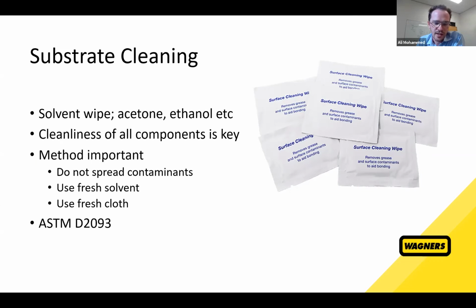Just a few notes is that when you're doing this cleaning process, everything has to be clean. So if you have a contaminated substrate and you wipe it with a clean cloth, you should never re-wipe that surface with that same cloth. You should always be using something clean on that surface every time. Otherwise, you'll just be redistributing that contaminant back onto the surface as you wipe over and over, so to speak. So you want to use fresh solvent, fresh cloth, and the right wiping methods. You can either develop your own wiping method, or there's a bunch of standards out there that you can use to see what the industry uses. Do you wipe in one direction all the time? Do you wipe in two directions, etc.? So there's definitely standards out there you can look into yourself.